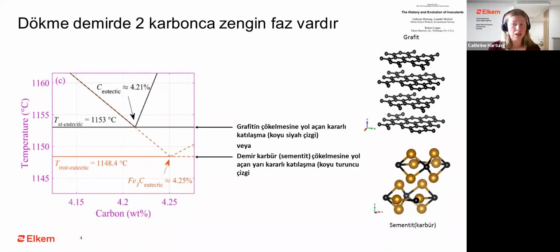A majority of the commercial cast iron grades rely on carbon coming out in the form of graphite to obtain the required properties, and solidification according to the metastable system needs to be avoided. From this iron-carbon phase diagram, we see that the temperature window between the stable and metastable system is 4.6 degrees in this case, or around 5 degrees. But fortunately, cast iron is much more than iron and carbon. A good thing is that all the other elements in cast iron increase this window from around 5 degrees to around 60 degrees.